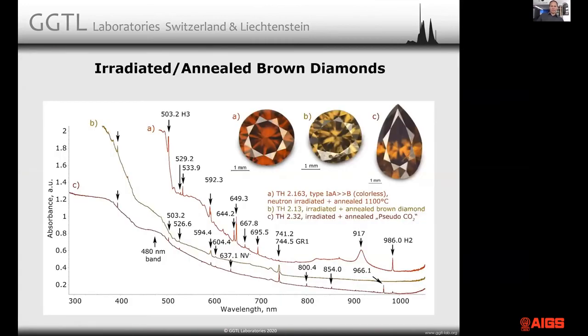Okay, these are 3 stones that are all brown and treated. A is an orange-brown, B is a yellowish brown, and C is an orangey brown stone. They've all been produced by treatment. A has been produced by neutron irradiation. That stone was perfectly colorless before treatment. We treated it by neutron and made it black, opaque black, really black. And then we annealed it to 1100 degrees. At about 800 or 900 degrees, it got this beautiful orange-brown color and this very complex spectrum seen in trace A. So this is one way.